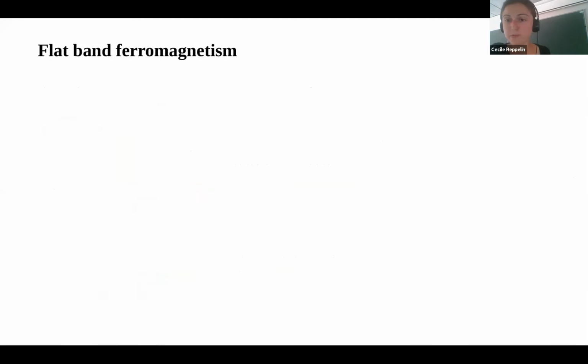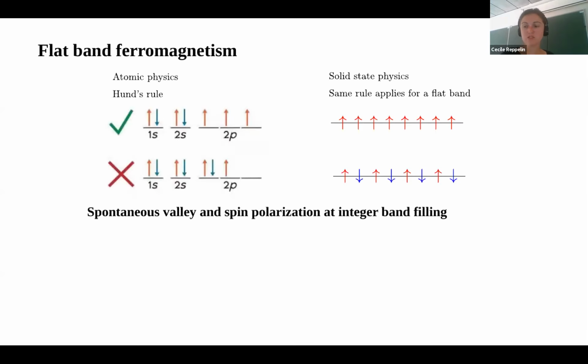So after this phenomenology, let's go into some microscopics. This is a phenomenon that's often called flatband ferromagnetism, and it can be linked to Hund's rule in atomic physics. So Hund's rule tells you that when you have atomic orbitals that are degenerate, it's energetically more favorable to fully fill one level with electrons of the same spin rather than having electrons with opposite spins. So here it's basically the solid state equivalent of this rule that is observed in magic angle twisted bilayer graphene, and which shows up through a valley spin polarization at integer band filling. Well, at least that's what you expect from Hund's rule.